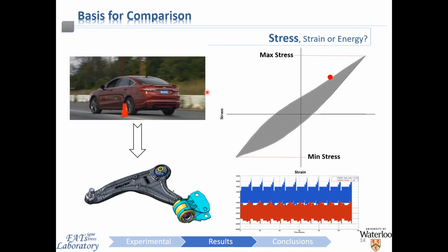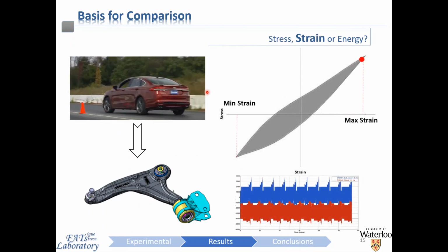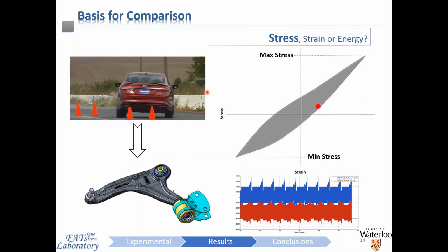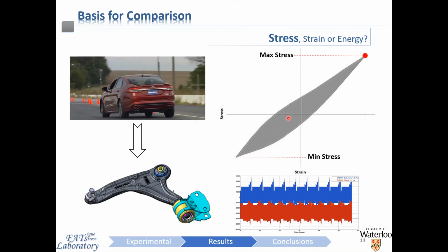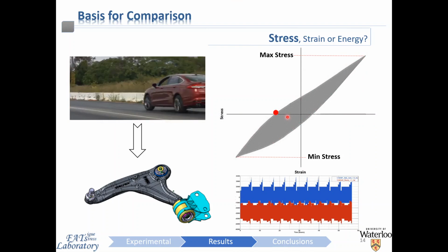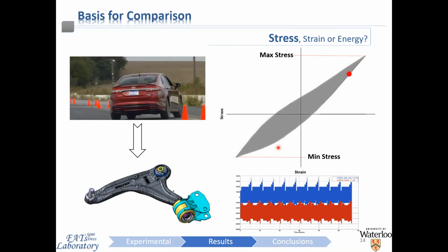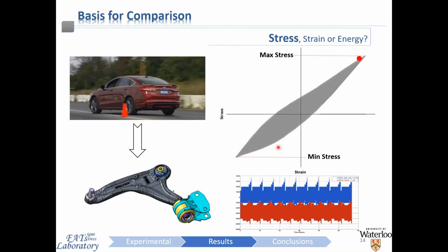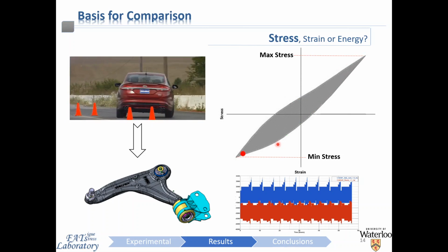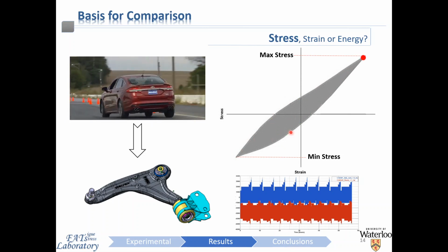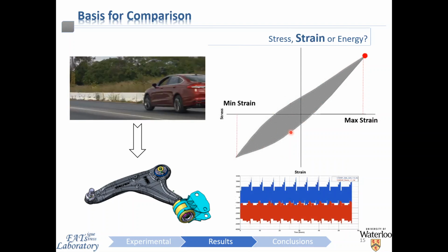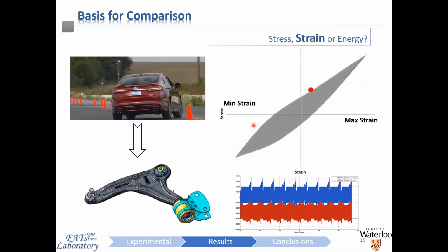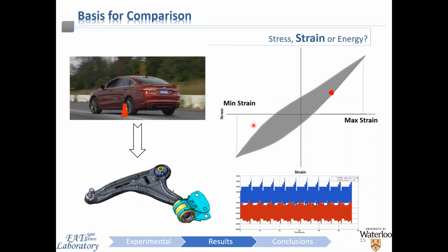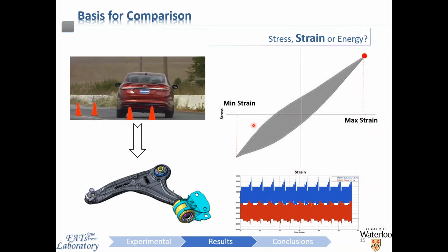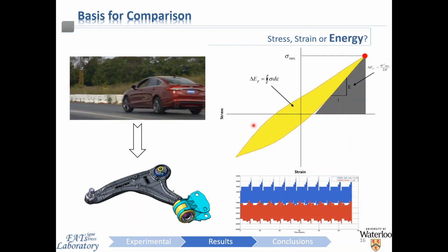The first approach employed is to use the stress reversal as the basis here, so we can see that indicated at the top and bottom here, for characterizing the fatigue life. So if we impose the minimum and maximum stresses as the boundary conditions for the experiment, then we measure the resultant material response. So the key output for this is an SN curve from this style of test. The second technique is to control the maximum and minimum strain amplitudes and measure the stress response of the material. So the key output from this style of test is a strain life curve, which is generally used to model the material behavior in the automotive domain.